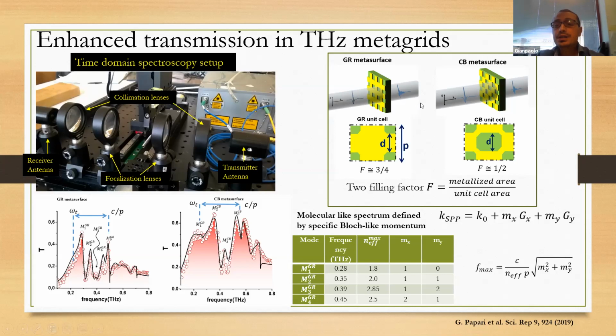The two grids we are using to make sensing are just made by a foil of FR4. It's a commercial insulator made for circuits and PCBs, 160 micron thick, this green part. And there is a metallic grid, in this case in two shapes: just a grid, which we have called grid metasurface, or in the shape of a chessboard, CB metasurface, which are characterized by two different filling factors.